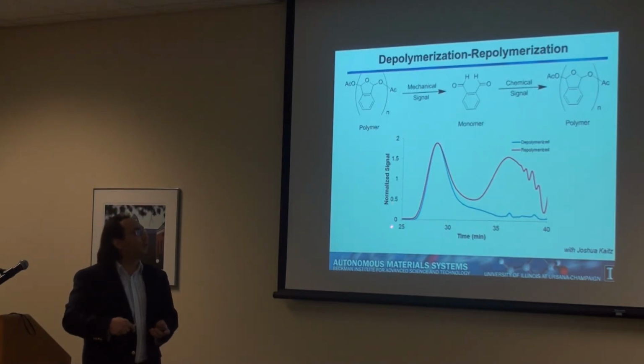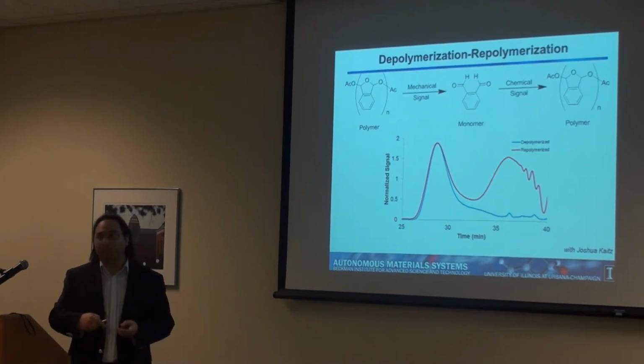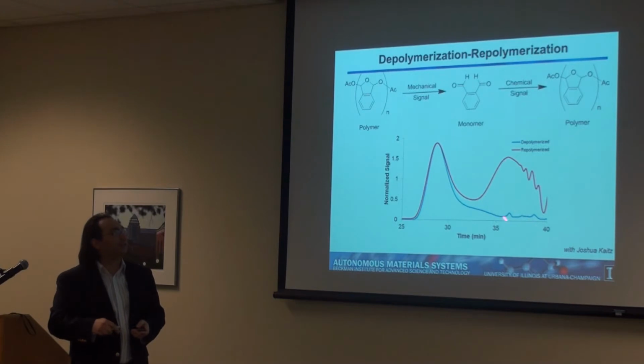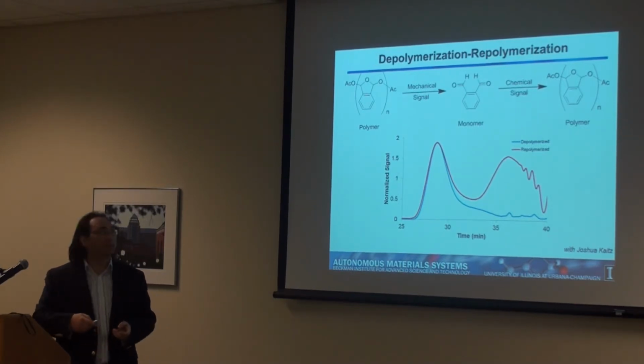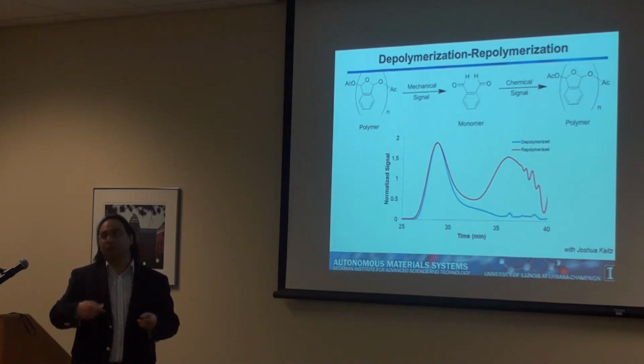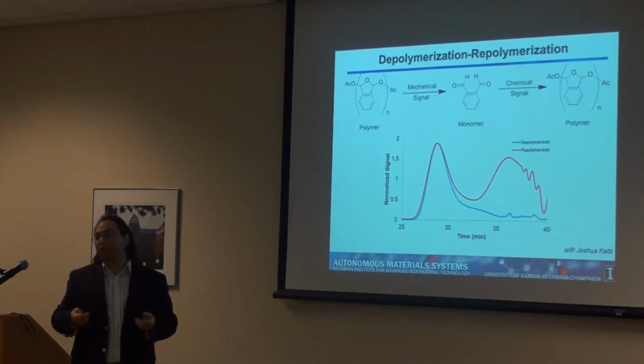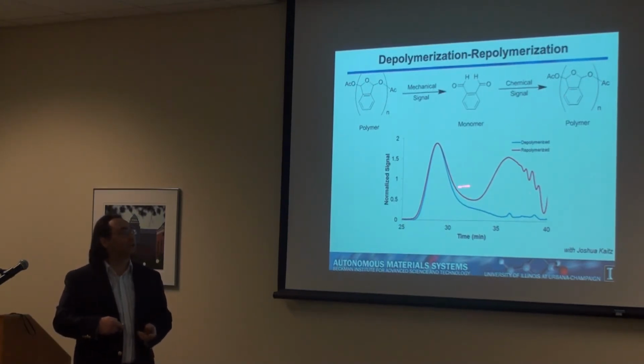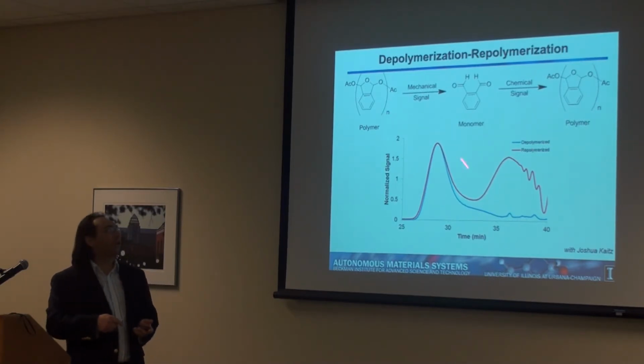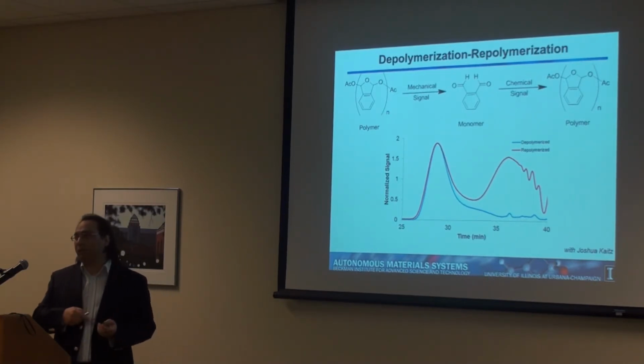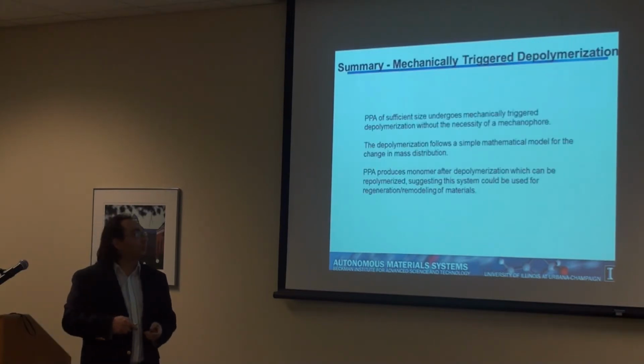And that's what it did. So basically, this is a gel permeation chromatography. The blue one is the remaining polymer that did not depolymerize during the mechanical stress. And then we take the same solution, put an initiator in there, we do the polymerization again, and we get a new polymer with lower molecular weight in this case, but just to show you that we can make new polymer in there while keeping the previous one in there.